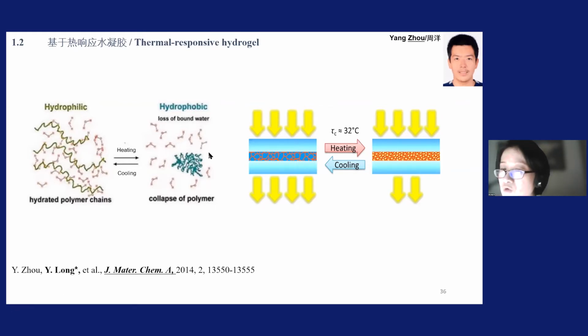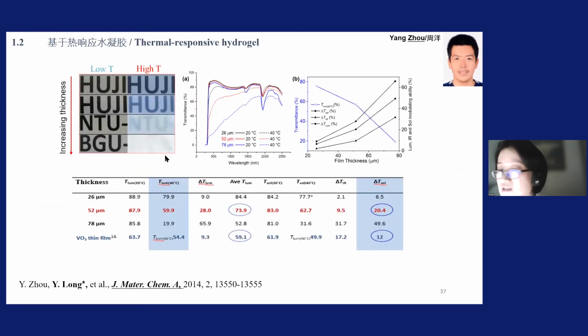And as I said before, it works with this phase separation concept. You can say the concept is very simple, right? You can imagine this is winter time and the summertime, if you control the different thickness, you can control it from very opaque to very translucent. The good thing is that now you can tune the visible range. VO2 only tunes in the IR range, but the hydrogel tunes more in the visible range. So compared with VO2, the average TILU is about 60 and the delta TISO is about 12. But if I use hydrogel, I can get this nearly double, delta TISO from 12 to 20, and the TILU from 60 to 70. So both are much enhanced.